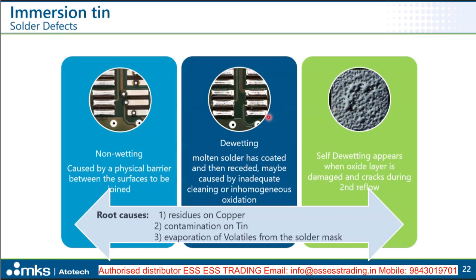A second failure can be dewetting. That means the solder did wet the surface first, but then receded from the edges and dewetted, and finally non-wetting, meaning really the layer did not wet at all and the solder remains in corners or certain areas and does not fully wet the surface.